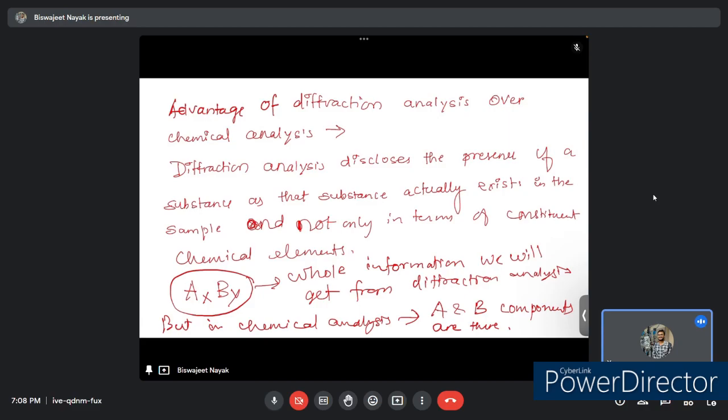So a collection of diffraction patterns from many substances allows identification of an unknown by recording its diffraction pattern and then locating it in a file of known patterns, one which matches the pattern of the unknown exactly. So the collection of known patterns has to be large if we are going to look at any random sample.